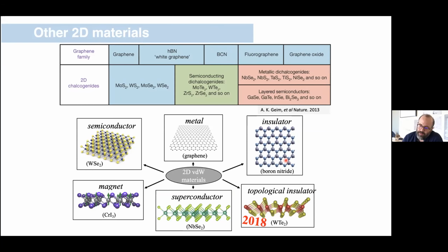So one thing we've been doing is learning to appreciate that there are a wide variety of van der Waals materials, not just graphite. And by van der Waals materials, I mean materials where the structure is layered such that the interlayer coupling is weak van der Waals bonding, but the intralayer bonding is much stronger. All these materials share the similar property that they are, quote, exfoliatable. We can isolate a monolayer of each of these materials in the same way that I just described, and we can put contacts on those monolayers.